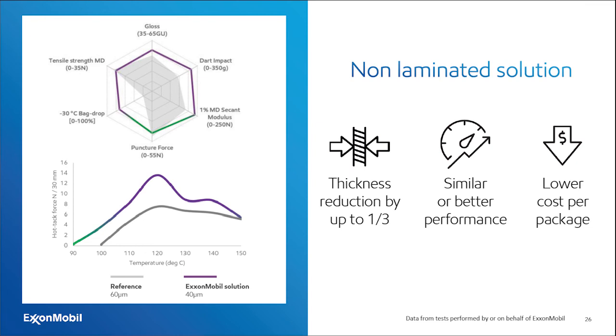So in this case, we prove a thickness reduction of up to 1/3, similar or better performance, and lower cost per package. And I want to make a comment here on the cost side, because we should keep in mind that the performance polyethylenes will be more expensive on a kilo basis. But thanks to the fact that you need to use far less, the cost will be lower per package. So this is something that's very important to keep in mind if you want to go for these kinds of developments: all cost or price discussions should happen on a square meter basis and not a kilo basis. So this is the non-laminated solution.